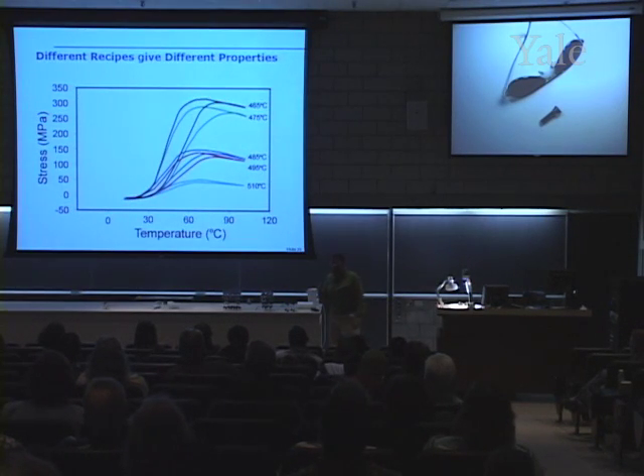Well, here's those curves, those hysteresis curves that I talked about a moment ago. And we're looking at those examples that I showed just moments ago, where we have the high temperature case and the low temperature case. You can see that the hysteresis, or the height of these curves, is significantly different. We have a low hysteresis curve at high temperatures, and we have a high hysteresis curve at lower temperatures. So once again, the object of the game is to create materials that have higher hysteresis curves. And what we can learn here is that lower temperatures are the way to go in order to create devices that will have larger forces. Does that make sense? All right, so what we're doing is we're cooking and we're relating it to the properties. And that's pretty much what material science is all about.